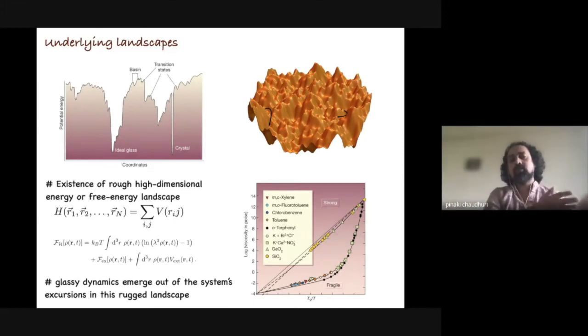As in the question that was asked just now, as I introduce this external field, roughness in the landscape slowly emerges, and this increasing roughness of the high dimensional space results in the system getting locked down into one such local minimum. So this energy minimization process is happening as the dynamics proceeds. This is how you get these large domains of green and small domains of red and so on. Essentially, this is an optimization problem in a high dimensional space.